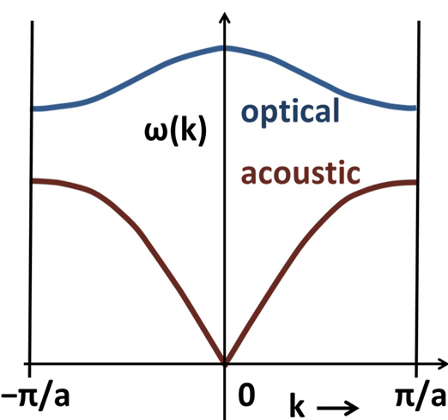The plus sign results in the so-called optical mode and the minus sign in the acoustic mode. In the optical mode, two adjacent different atoms move against each other, while in the acoustic mode they move together. The speed of propagation of an acoustic phonon, which is also the speed of sound in the lattice, is given by the slope of the acoustic dispersion relation, the group velocity. At low values of k, i.e. long wavelengths, the dispersion relation is almost linear, and the speed of sound is approximately omega over k, independent of the phonon frequency. As a result, packets of phonons with different but long wavelengths can propagate for large distances across the lattice without breaking apart. This is the reason that sound propagates through solids without significant distortion.